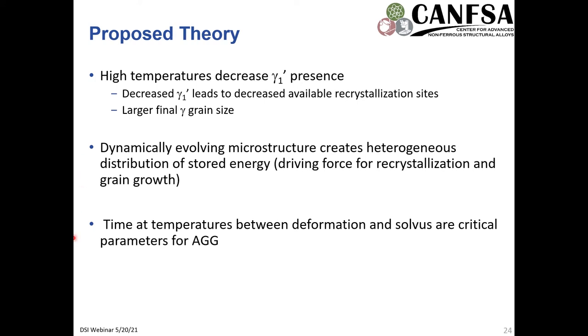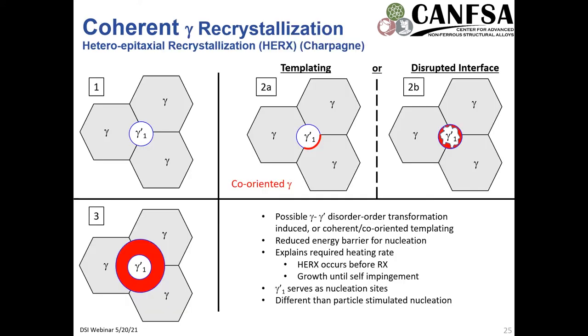And this time at temperature between the deformation and the solvus are the critical parameters for abnormal grain growth. And so going into a little bit more detail about the coherent gamma recrystallization through the heteroepitaxial recrystallization technique or mechanism that Charpagne has discussed, if we look here in the schematic, we have a primary gamma prime that's incoherent and existing at gamma grain boundaries. And if the gamma grains have a certain level of stored energy and a certain misorientation angle, then during heat treatment, you may have a templating mechanism, that is the gamma forming co-oriented with the primary gamma prime, and that could grow to consume the neighboring gamma grains.